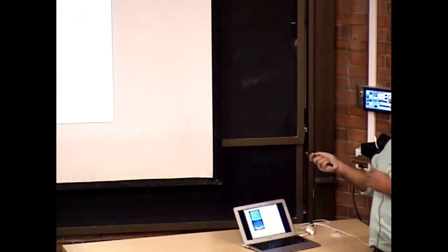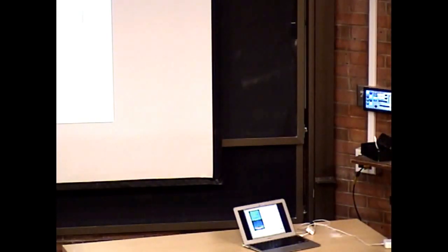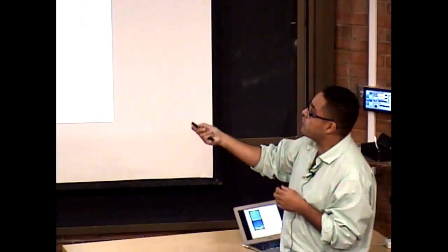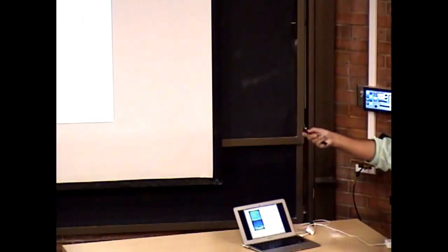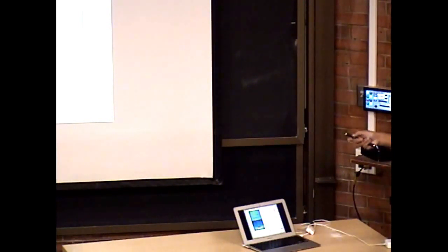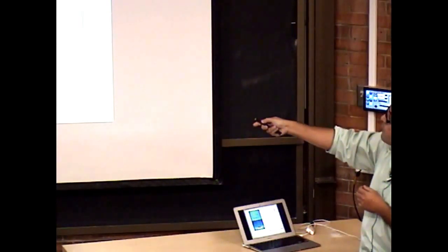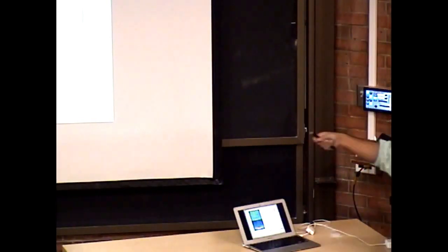Another thing that we do in my group is trying to study the physics of potentially spontaneous coherence formation due to strong exciton-photon coupling in optical microcavities. So here what we have are Fabry-Perot microcavities, in this case made with organic materials, but we study as well quantum wells, gallium arsenide quantum wells, and Fabry-Perot microcavities of these. The photon dispersion in an optical microcavity is quadratic, and you tune your microcavity so that somewhere around here it would intersect with the resonance of the exciton.